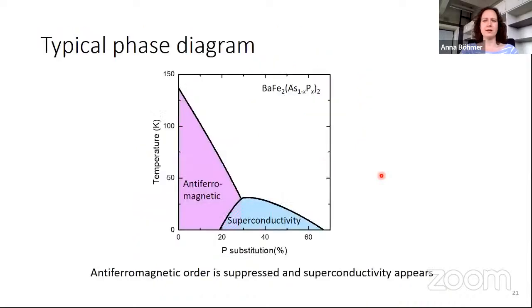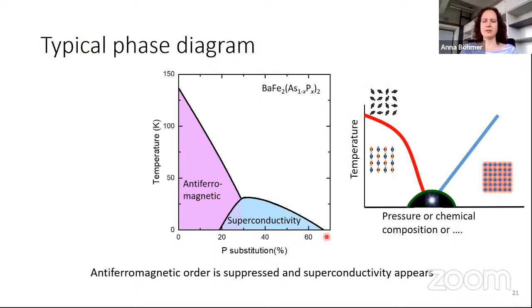And let's look at the typical phase diagram here. So again, I have temperature, and now I have chemical composition here as my tuning parameter. The material specifically is barium, iron 2, arsenic 2, and then a little bit of phosphorus in there. What we find is an antiferromagnetic phase and a superconducting dome, very similar to that suppression of magnetism and a new phase emerging, as in the introduction.